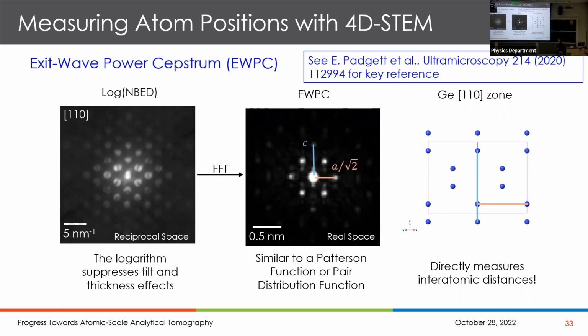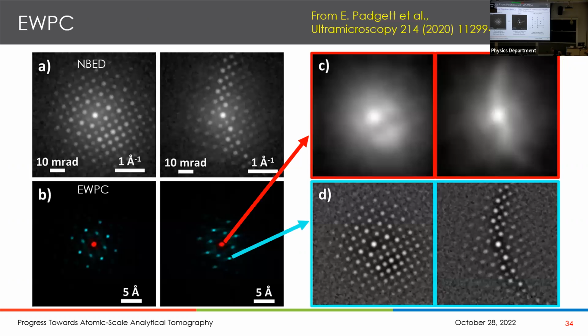And the way this is done is you defocus the probe to maybe 5 nanometers. You want to map something, let's say you want to map something that's a micron, you do a 5 nanometer spot, then you move about 2.5 nanometers and do it again, and again, and again. Then you move on, or step scan is another word for it. And that might take 1,000 patterns, but you can record these at, some of these cameras are doing 10,000 images per second.